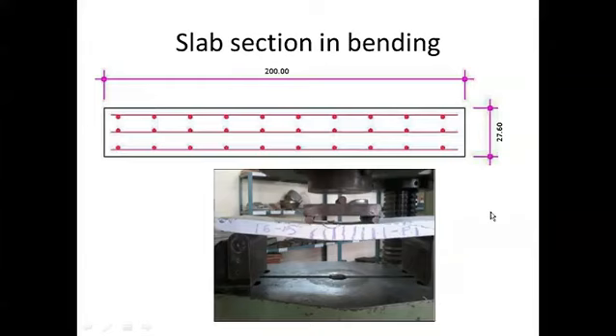This is a typical setup for ferrocement having 3 jalis. Now this was a test where we had one more jali at the neutral axis. What was observed is that the test results for just 2 jalis, without any jali at the neutral axis, behaved exactly the same way as the sample with a jali at the neutral axis.